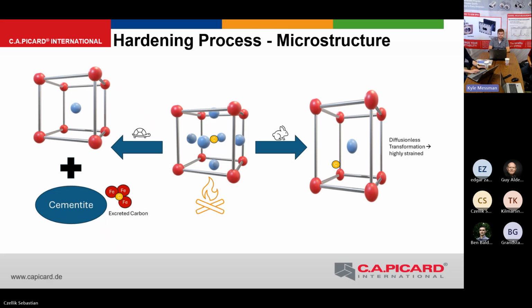And here's the lattice. For the hardening process, you know the iron-carbon diagram. I don't want to show it here. I just want to show what is happening. So when we heat up a steel, in the middle we get a cubic face-centered lattice. And as we have heat in there and the atoms can move because they have energy, carbon finds space in the middle or at other positions in the lattice. And now two things could happen. When you cool down slowly, it will go back to the cubic body-centered as it was before heating up, and you will have the carbon as cementite as a phase next to it. But that's not what we wanted.